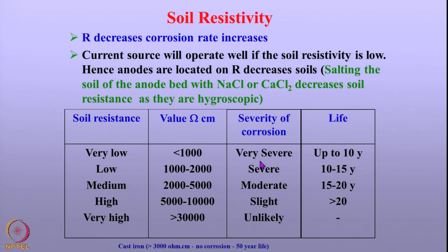The severity of the soil towards corrosion is also related to the life of the pipelines. And so there is an indirect relation between the soil resistivity and the life of the pipelines. In fact, you can see that if the soil resistivity exceeds 10,000 ohm centimeter, the life of the steel structures can be beyond 20 years. And if it is cast iron, then the life can be even beyond 50 years.